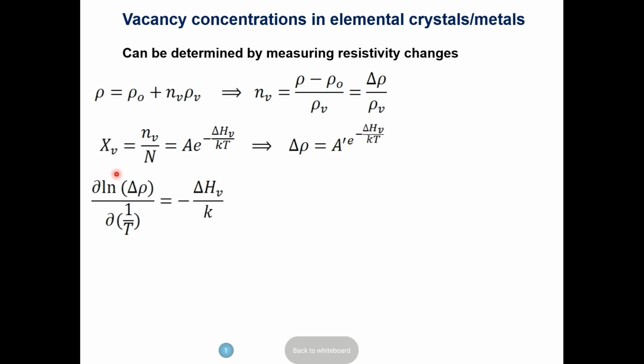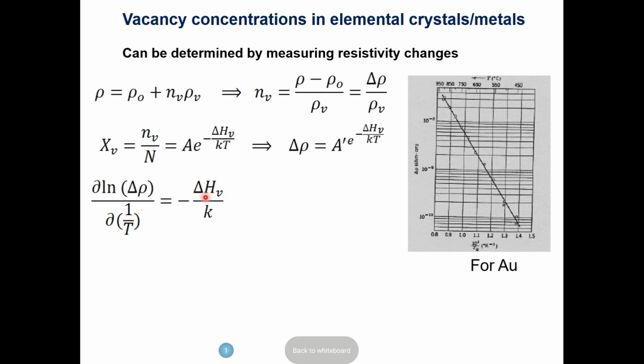So if you look at the change in the logarithm of that resistance, take the negative slope, you should get this enthalpy. In other words, if you plot the logarithm of delta rho versus 1 over T, you should get a straight line, and the slope of that line gives you the enthalpy I talked about. This term is obtained from the change in electrical conductivity by measuring delta rho, and this has been done for many metals.